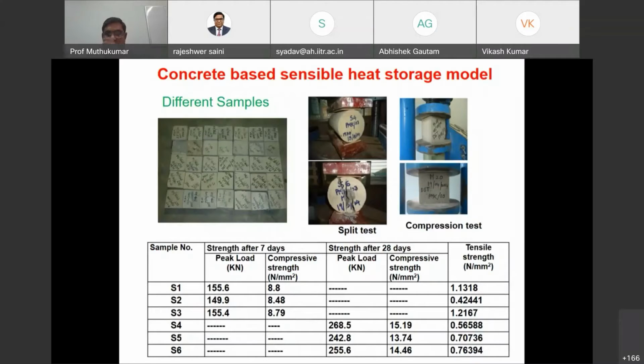In the concrete-based one, we have done a lot of studies, and before choosing the concrete composition, we developed several such concrete modules, based on the standards like M5, M10, M15, M30, etc. And based on this ISI standard, we have developed them. All these blocks went through successive compressive and tensile stress tests, and then we found out the respective strengths. Then the required composition for our thermal storage application is selected, based on the high strength versus the cost.